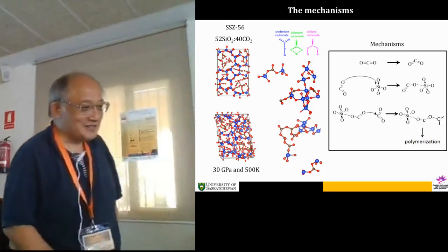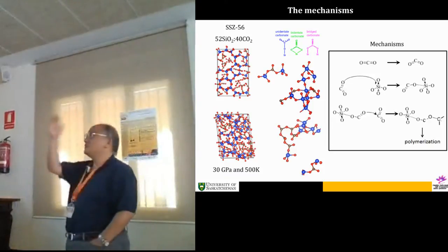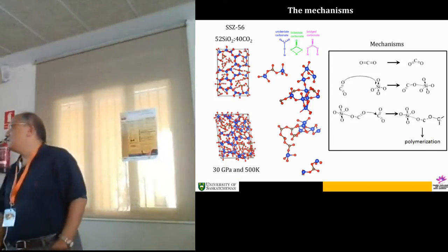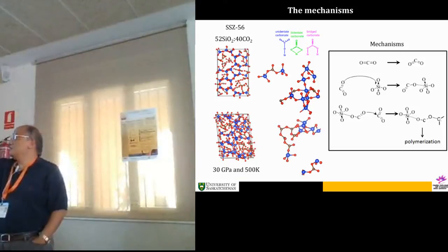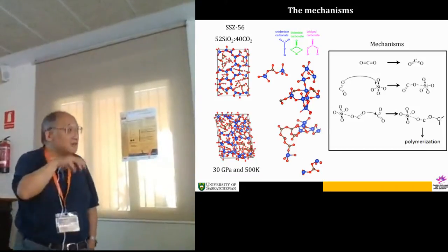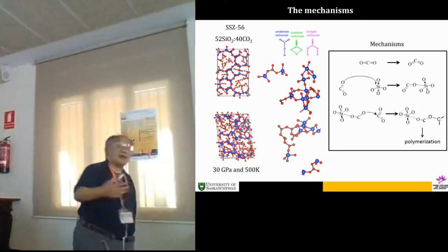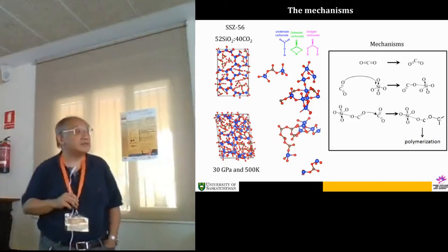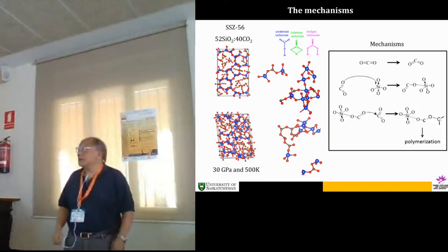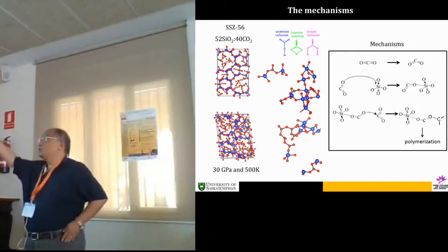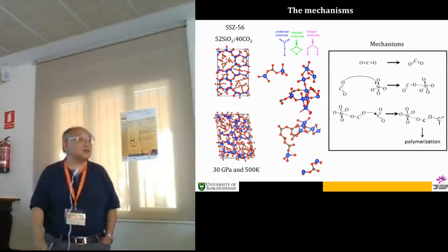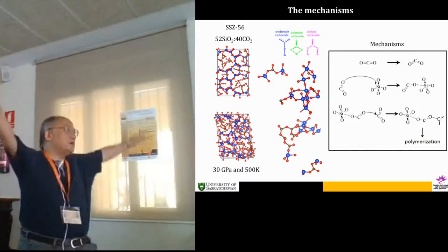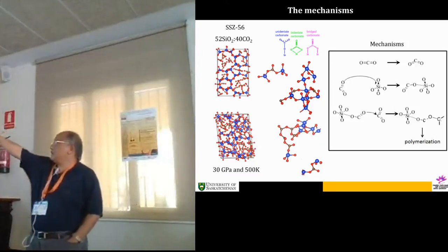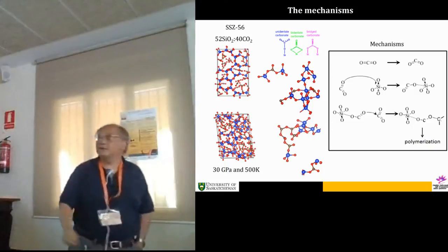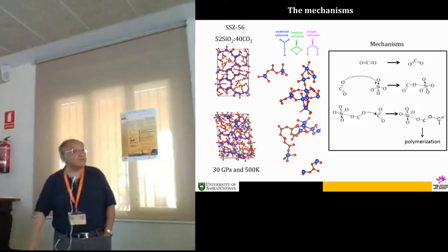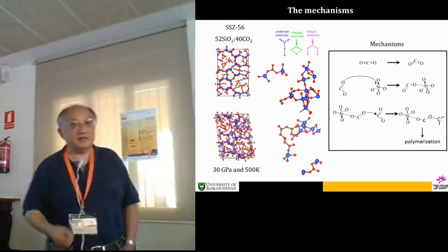So, well, you can do the calculation. In this case, actually, it's not a model. We take the same zeolite, load it with the same concentration, and then heat it like hell. And you can calculate and analyze the structures. Those are the structures where you find how the CO2 reacts with the zeolite, and gives rise to vibrational frequency. And that's the vibrational frequency they highlight to show the formation of a CO2, SiO2 compound. So the added understanding is we know the mechanism. When you hit the CO2 at that pressure and that temperature, there's a big fluctuation, a vibration of the oxygen. When it bends, we attack the lone pair, we attack the SiO bond and form the first linkage, and eventually it polymerizes. So that's the added information you get from the excellent experiment.